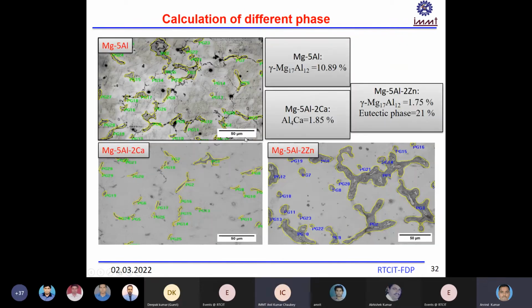Here you can see that we have calculated the volume fractions of the phases by the image analysis method. Different volume fractions were calculated for the different phases and then added together, and in this alloy you can see the gamma phase is around 11%. You can see the points P27, P15, P24. All these points were calculated with the help of the software, and it is found to be around 11%.